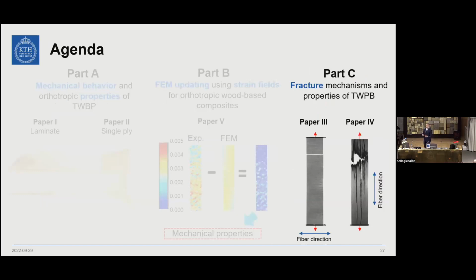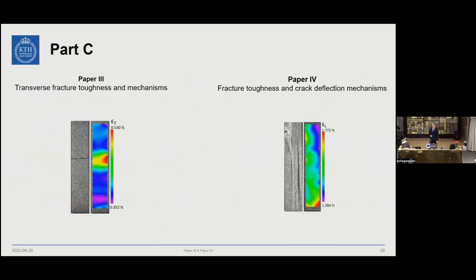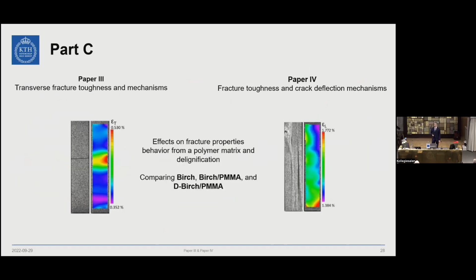Now, in the last part, we want to investigate the fracture mechanisms in transparent wood and wood-polymer composites. We can utilize these strain field measurements to identify the elastic properties of this material and also the fracture properties by doing one test. So we can utilize what we learned from part B. And specifically here, we want to look at these localized points. What are the reasons why it fractures? Why does it look like this? And we will compare native birch PMMA and the delignified birch PMMA composite.